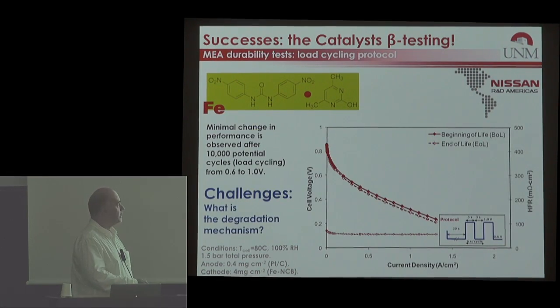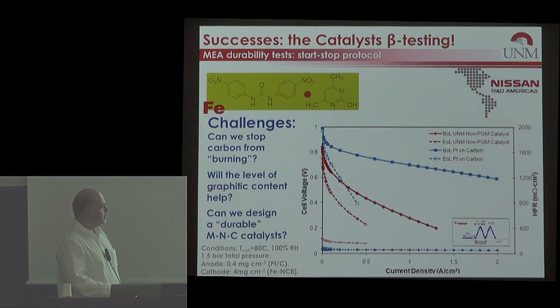But when it happens, then you learn that your stability in cycling in the so-called test driving protocol between 0.6 and 1 volt is practically meeting all industrial standards, and stability in stop and start between 1 volt and 1.5 volt does not meet industrial standards. But on the other hand, this is a comparison with an industrial catalyst, highly advanced platinum on carbon, made by a company called TKK, which is an industrial standard. This is how TKK catalysts burn under the same conditions, between 1 and 1.5 volt.